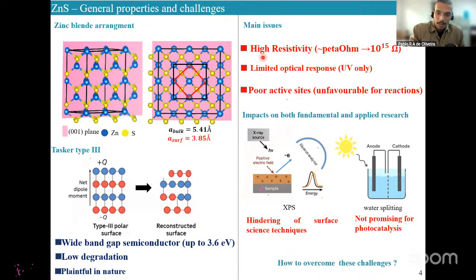So from the fundamental point of view, I highlight here some experiments done with XPS. Essentially, you have photons coming to the surface and exciting it, so electrons are ejected toward the electron analyzer. As your system, in the case of ZnS, is an insulator, the hole left behind is not fully compensated because there are no available mobile carriers to compensate this hole. Therefore, the positive electric field that results on the surface will attract the electron that was ejected first. This interaction will decrease its kinetic energy, and usually when you have insulator systems, you have a huge shift in your XPS spectrum.